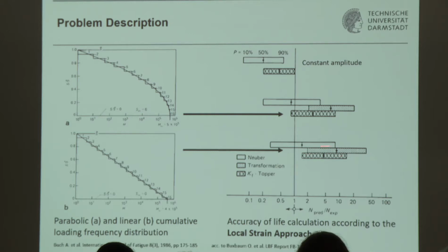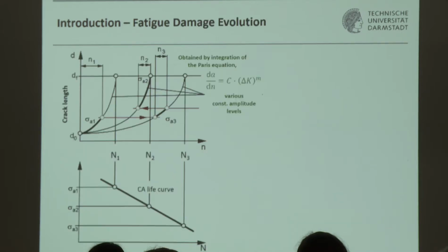And if you look at these bars, you will find factors in a good case of 2 on the non-conservative side, going up to more than 10, approaching 100. And so the situation is a bit worse for the straight line distribution than it is for the parabolic distribution. And an equally old idea is to ask fracture mechanics whether this technology or this approach is better to arrive at more accurate predictions of lives to crack initiation.